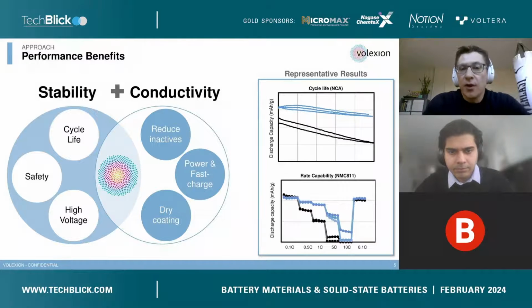So in terms of benefit that we provide to lithium-ion batteries, I think it comes in two categories, because we're really at the intersection of a surface protection technology and a conductive additive technology. On the stability side, what we routinely observe at Volexion is a significant increase in cycle life of a lithium-ion battery. 2 to 3x is pretty common. Better safety, particularly for nickel-rich material, because we prevent oxygen evolution, which Nikhil is going to tell us about in a few minutes. And finally, we enable high voltage operation with current materials and with emerging materials.